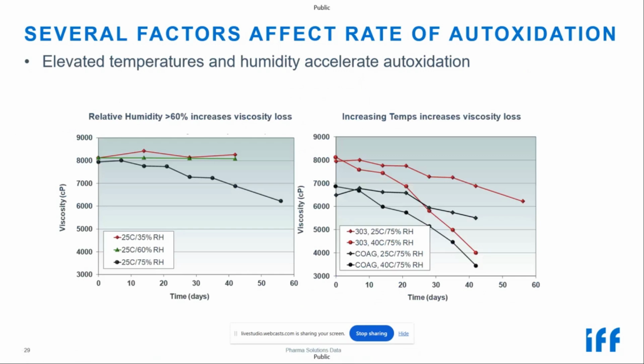Other factors that impact the observed viscosity decay rates of POLYOX PEO are temperature and humidity. So we'll start with humidity. On the left, we put small amounts of PEO into baggies. We kept the temperature constant at 25C, and then raised the relative humidity from 35% to 60 to 75%. So these samples at 25C with 35% and 60% relative humidity conditions showed pretty good stability over the 40-day time period that we were measuring.